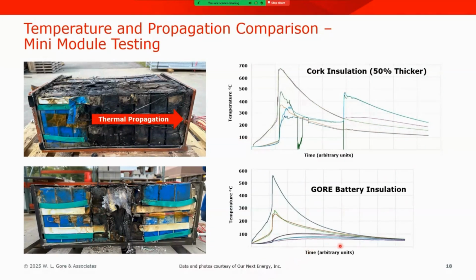And in fact, if we look at now the thermocouple measurements, you see that the most remote thermocouples barely moved above ambient and didn't approach anything close to 150 degrees C. And then the closer thermocouples to those cells really only achieved slightly above 100 C. So these photos and this data were provided by one of our early testing partners, which is Our Next Energy. And based on the results from these experiments, Our Next Energy has provided several conclusions.